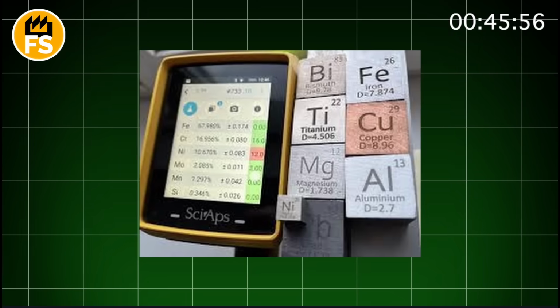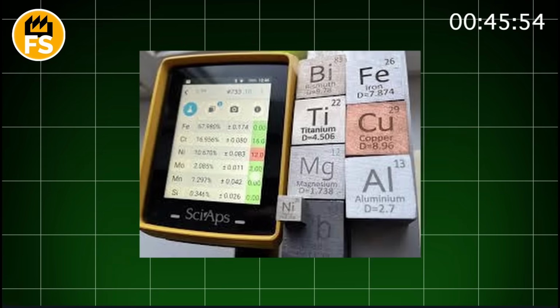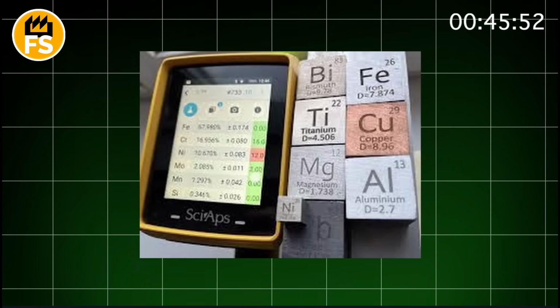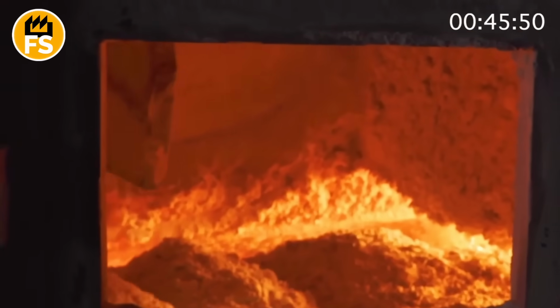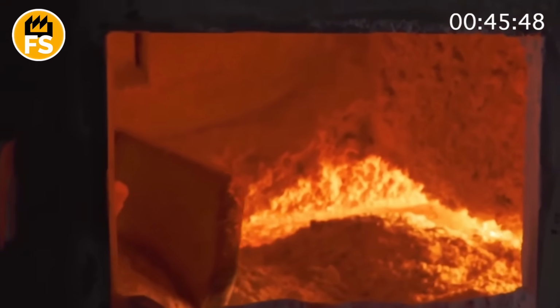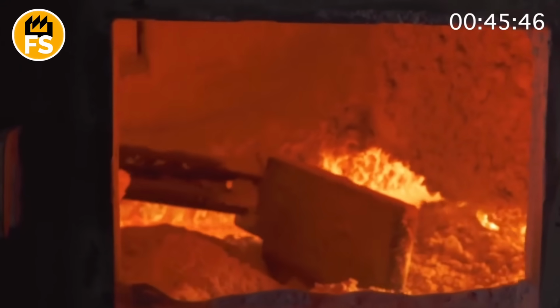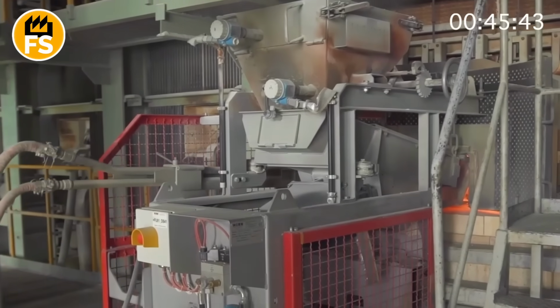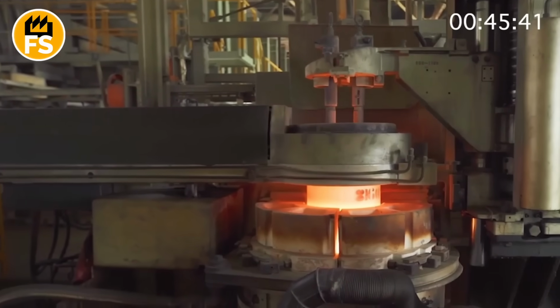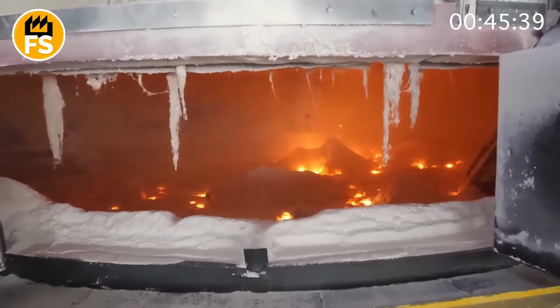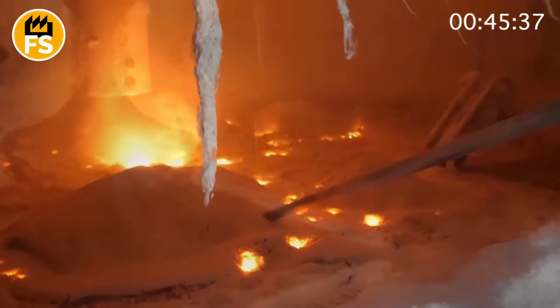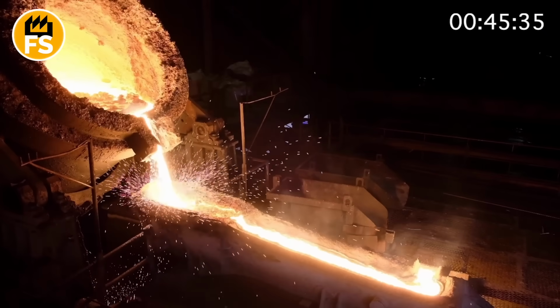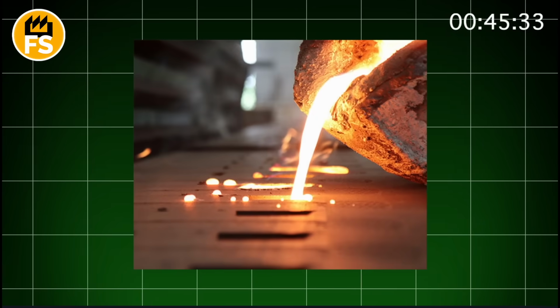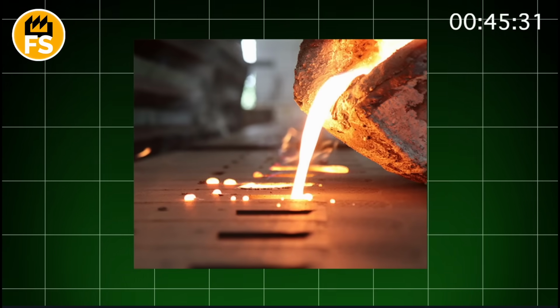Based on these analyses, precisely measured portions of alloying elements are added to the melt. Manganese for wear resistance, silicon for strength, carbon, and vanadium. The goal is to obtain a unique chemical recipe for steel, optimized for the extreme operating conditions of a railway wheel. When the steel reaches the ideal composition, the furnace is tilted, and a stream of white hot metal weighing tens of tons is poured into a huge ladle.